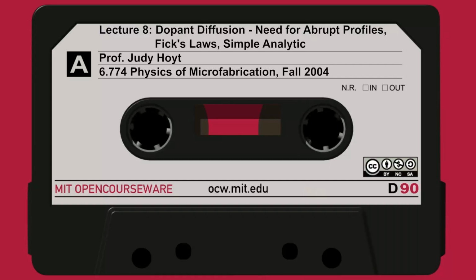So in fact, analytically, or in exact sense, the solution which satisfies Fick's second law is written down at the top of slide 31. The concentration is equal to C prime over 2 times the quantity in square brackets, 1 minus the error function of the argument x over 2 times the square root of Dt. And we can write this as C sub s times the complementary error function of x over 2 times the square root of Dt, where the second equation and third give you the definition of what we mean